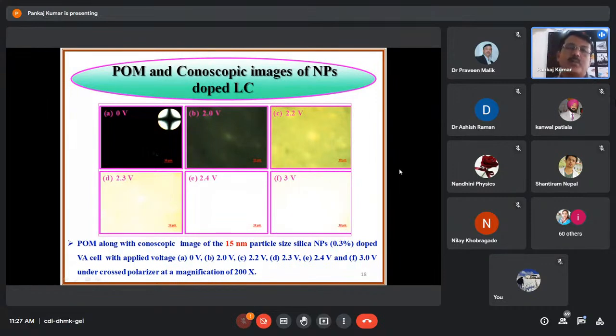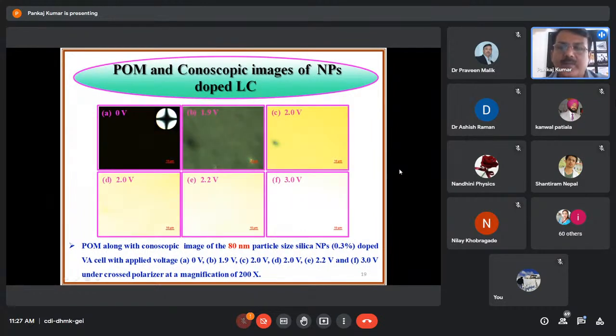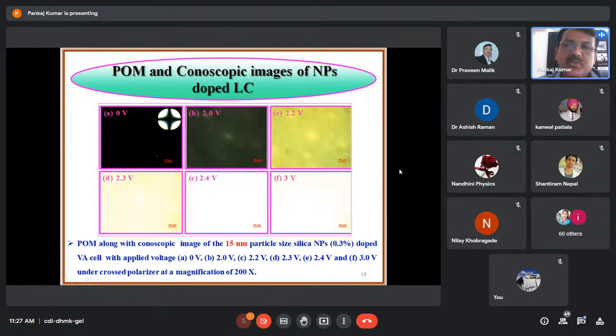So you can see here the perfect dark state as well as the perfect bright state. I would like to compare these states with the commercially used polymer nanoparticle doped VA cell also. Here you can see the POM image of the 80 nanometers. In case of the 80 nanometer, if you see the previous slide, 2.0 volt.